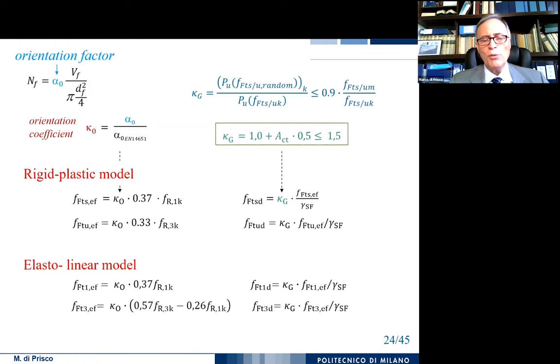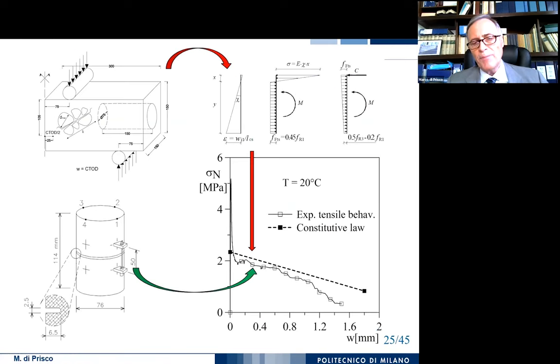And for this reason, at the end, we try to adopt in the final design expression a factor which is correlated to the orientation coefficient, what we measure and what we can compute in the classical EN 14651. And the KG is another factor which essentially gives us the possibility to go from the characteristic value to the average value, because we know that for a redundant structure we go towards that direction. And so at the end, the two models introduce also these two factors, and we arrive to define the design value by using both the factors and the classical safety coefficient, which is considered equal to 1.5. Well, we can check what we did.